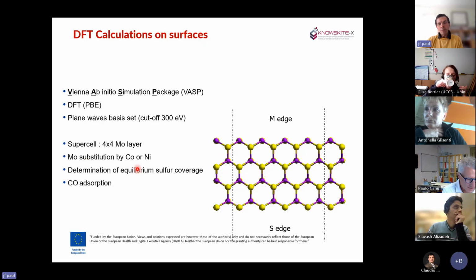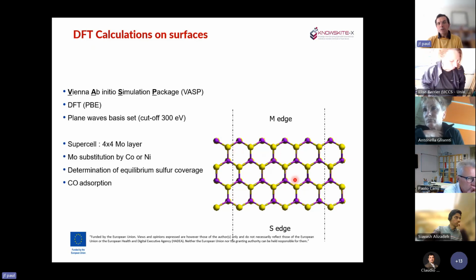The second problem is to build the cell. Here we have an example of a 4x4 cell, 4x4 system to define the periodic cell. It means that we have four molybdenum atoms. It's a way to reduce the interaction between the CO because the cell is quite large. And the other system is that we have four layers of MoS2. And it means that we can consider that the first one and part of the second one will define the surface, and the other one will define what is supposed to be the bulk.